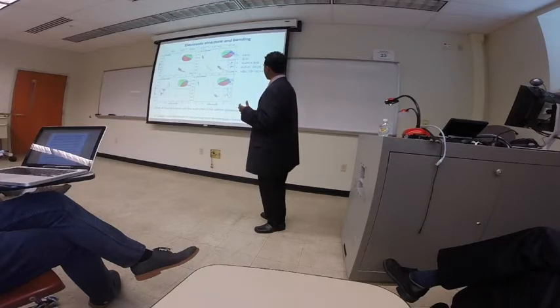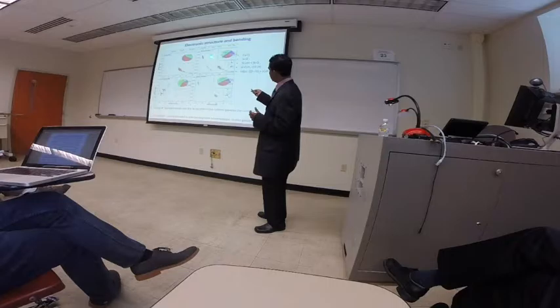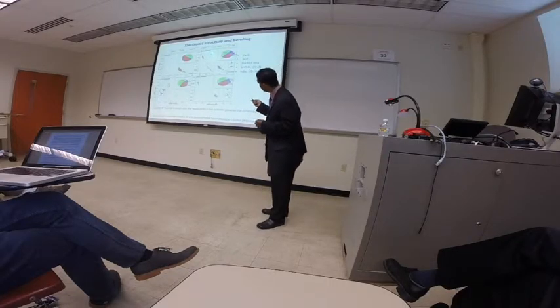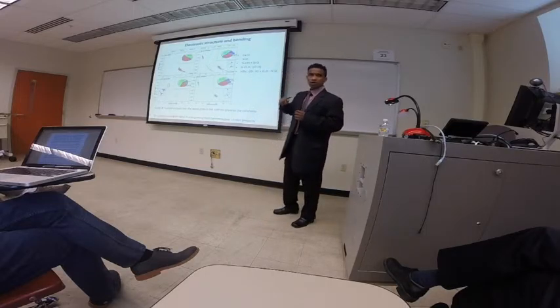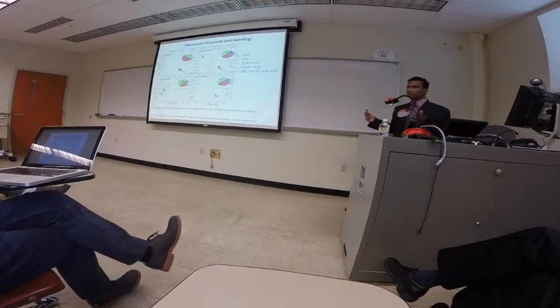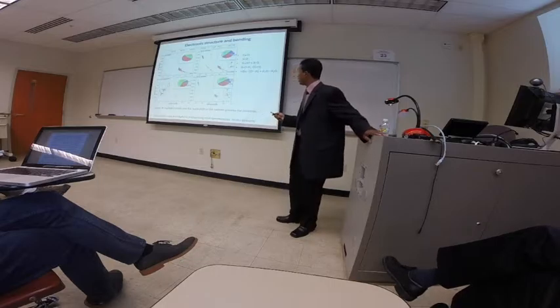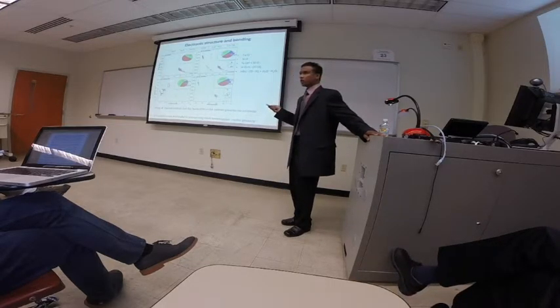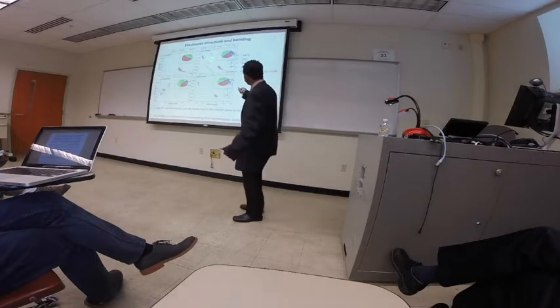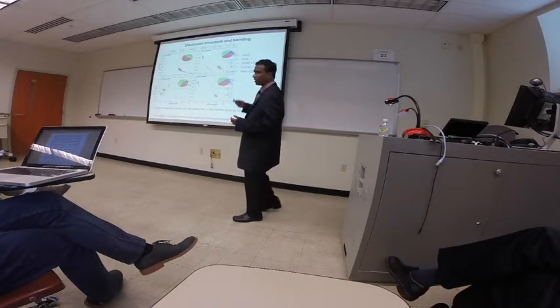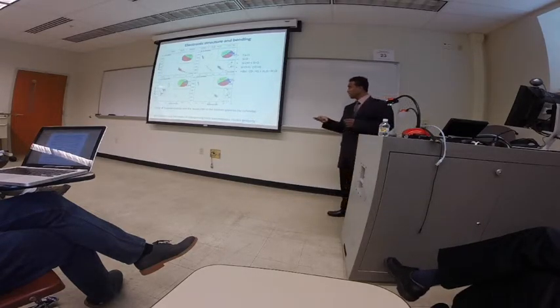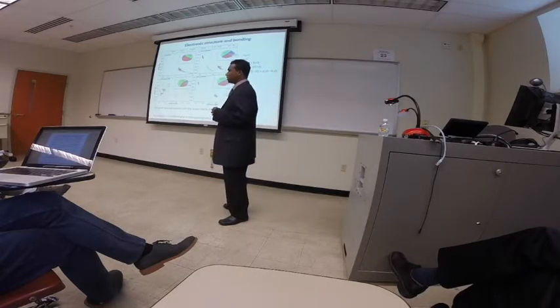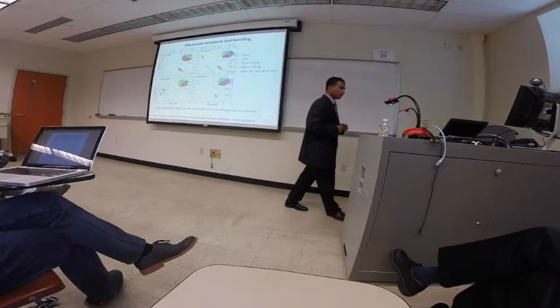Another thing that we saw was that this silicon oxygen bond length is very narrow, if you can see that. But bond order is much broader. And all the studies that analyze this think that silicates are very homogeneous. In fact, they're not. They may be structural-wise, but they're not strength-wise. How this comes into play is when you're trying to analyze a vibrational spectrum, because then the bond strength comes into play. And you can see, if you look closely enough, this is not just a broad band. There's some gap here. So we looked at this very closely, and we found out that silicates that are connected to hydroxyl have a lower bond order than the other ones. So this should be important information when you're trying to analyze spectroscopic data, for example.